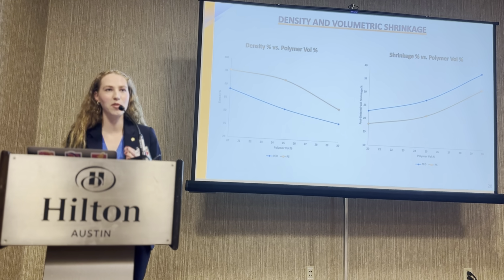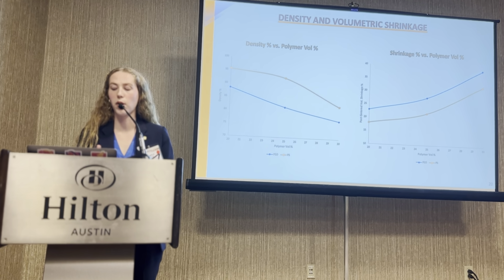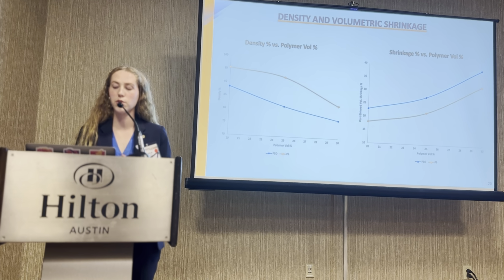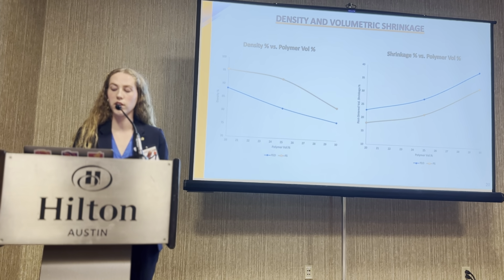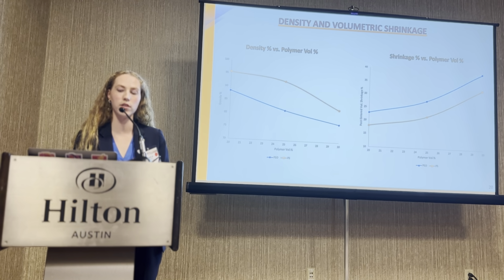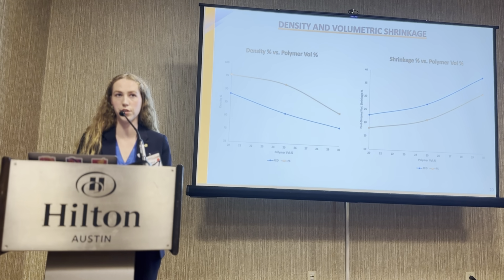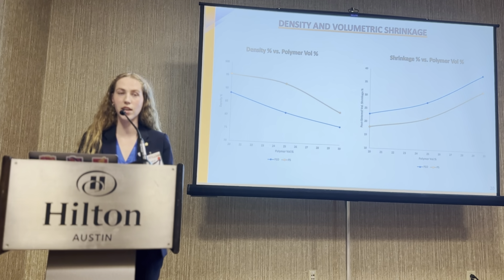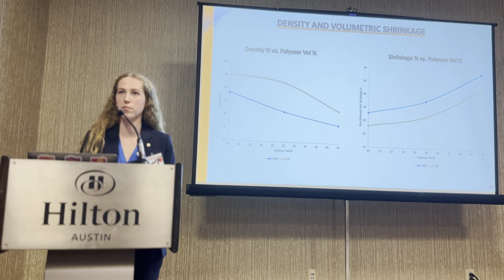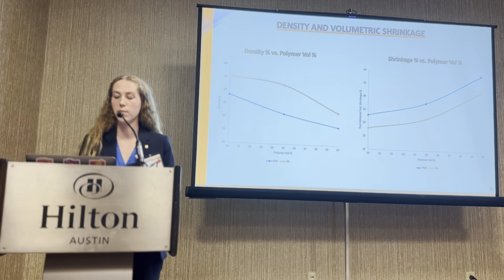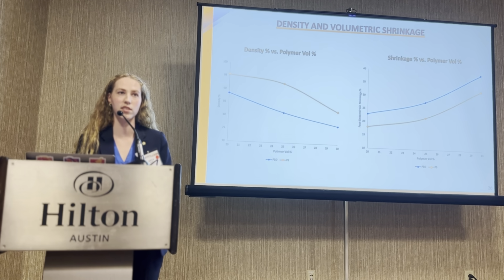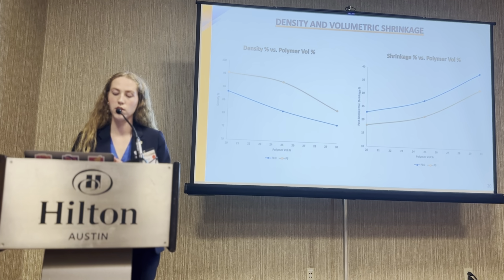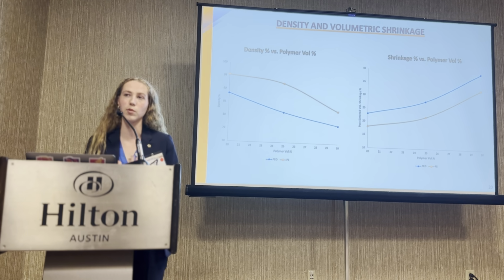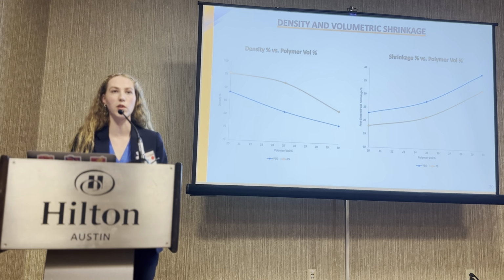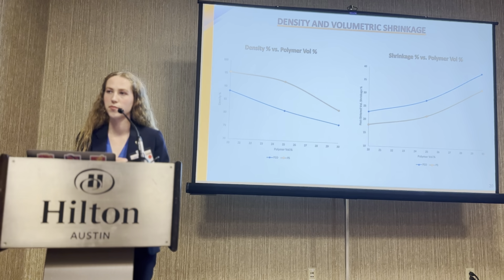So now let's get into more of a data-driven comparison of the polymer binder performances. As you can see, as the polymer loading increases, the density of the final part decreases and the shrinkage increases. Polystyrene had the highest density at 95% aluminum, but PEO had a highest density at 89%. The shrinkage for both binders had a very similar trend, but there was slightly smaller shrinkage from the polystyrene.